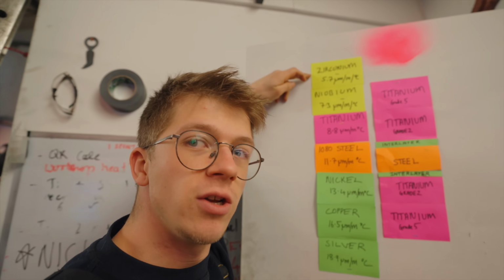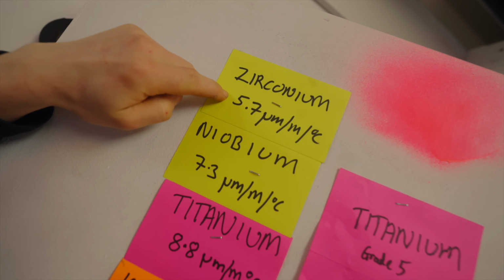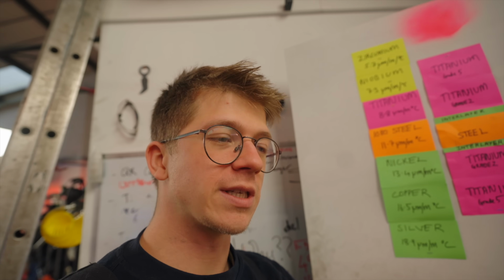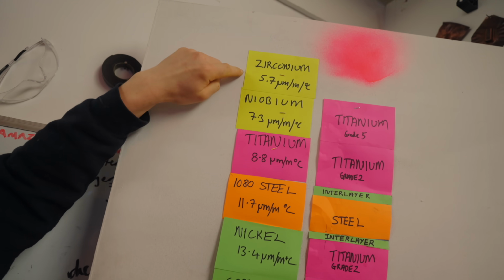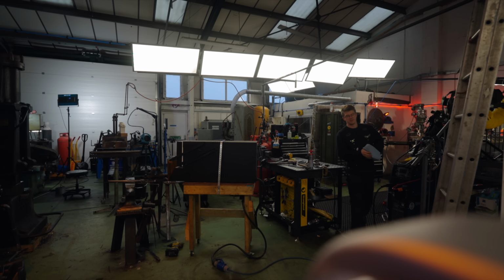So the zirconium was worse, and look at this. It has the lowest CTE. The niobium was less bad. It's got to be something to do with the CTE. My brain is going to be on the rev limiter trying to figure this out.